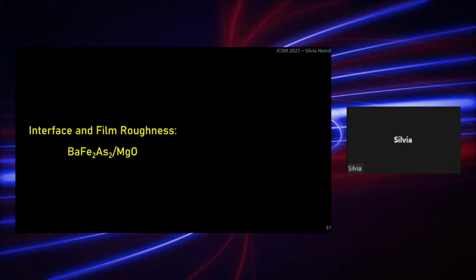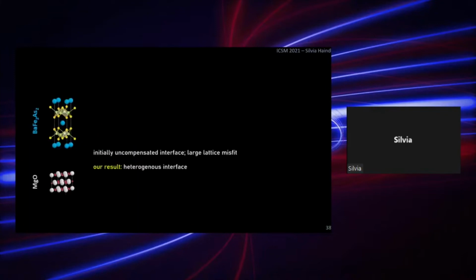So in the last section of my talk, I would like to share some information about another heterointerface, between the barium 122 iron pnictide and MgO. And I would like to show you how this interface is influencing the film roughness when you go to ultra-thin films. So we grow the barium 122 on MgO, which should be an initial uncompensated interface. And in addition, there is also a large lattice misfit within this system. So our result will be that we find a heterogeneous interface between these two compounds.